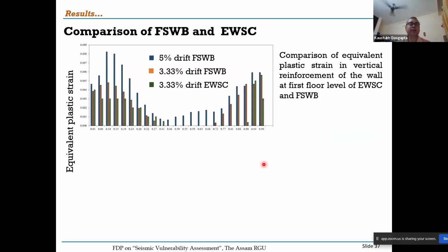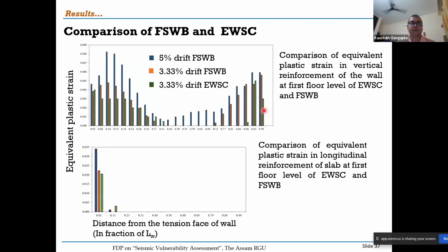When you look at the plastic strain, there are different ways of quantifying damage in Abaqus. Plastic strain in the equivalent form, that is one way. Depending on the region of your wall, the plastic strains are larger, right? And from the tension face of the wall, you have more plastic strain here. Okay, so at first floor level, we have tried to figure this out. This is how you get it. So the strains in the rebars are also getting changed. That is what we get.